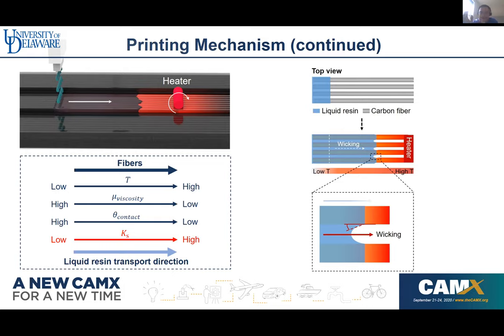Because of this, we can control the viscosity and the contact angle of the liquid resin with our carbon fiber. Actually, it depends on the geometry of the fiber structures, as well as the thermal and chemical properties of the resins. So in this case, we introduce another factor called Ks. This number will go from low to high. So this is the motivation for our liquid resin to spontaneously transport toward the higher temperature direction.